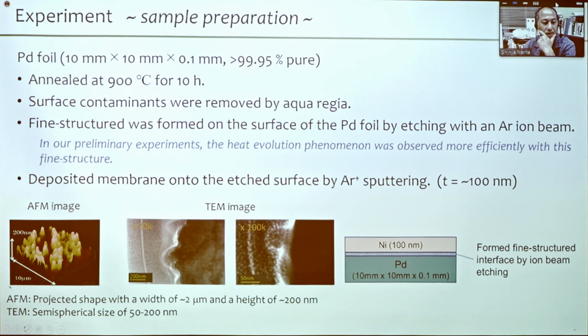So here are the microscopic images for the sample surface after etching. So this is the AFM, atomic force microscopy, image. So you can see the projected shape with the width of 2 micrometer and height of about 200 nanometer, like this. And more detailed image taken by the transmission electron microscope. Then you can see some semi-spherical shape of 50 to 200 nanometer here.